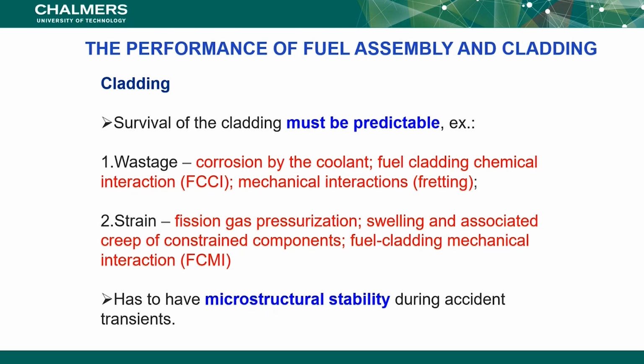And then, of course, we have here as well the fuel cladding mechanical interaction, and that means that eventually when the swelling is too much, the cladding and the fuel come in contact, so you don't have the gas around them anymore, but they will come in contact inside the tube. So in order to prevent accidents and thinking about all the steps we have been talking about before, it has to have microstructural stability during accident transients. So you have to know down to the microstructure what could have happened. So you know what type of material you have, and you know the potential defects which you can have, or the potential defects you induce, like the welding, and then you know the microstructural stability, at least at the higher scale. Next, please.